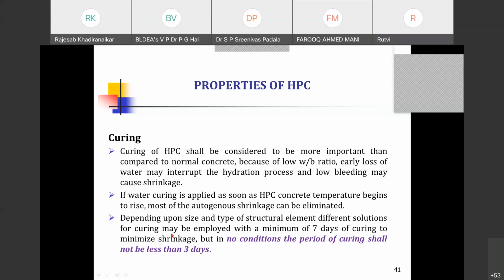That's why in some cases we resort to early curing of high performance concrete. If water curing is applied as soon as the HPC concrete temperature begins to rise, most of the autogenous shrinkage can be eliminated. Depending upon the size and the type of the structural element, different solutions for curing may be employed, with a minimum of 7 days of curing to minimize shrinkage, but in no condition shall the period of curing be less than 3 days. It doesn't mean that only 7 and 3 days.